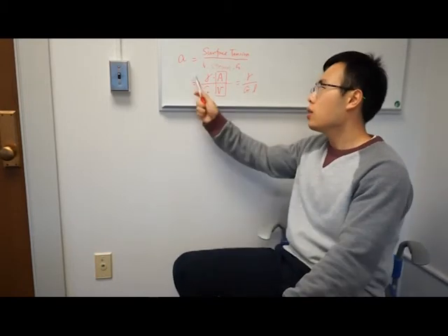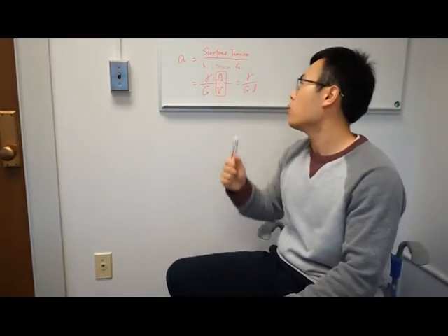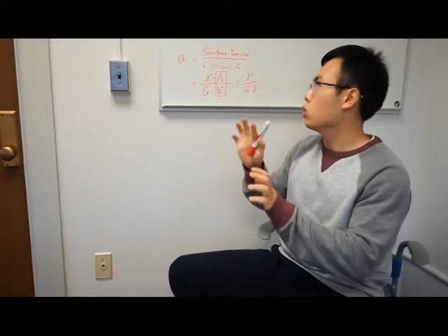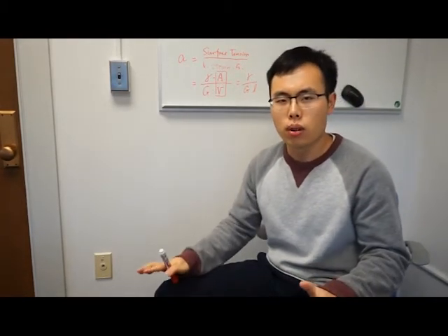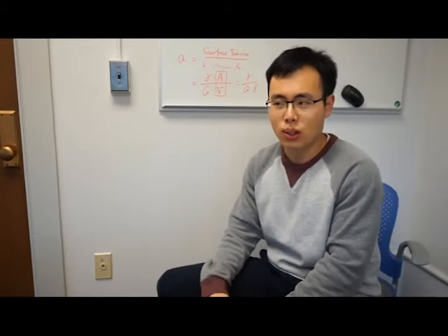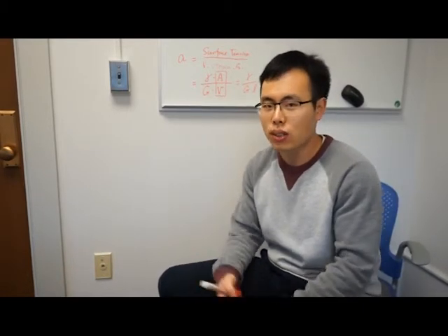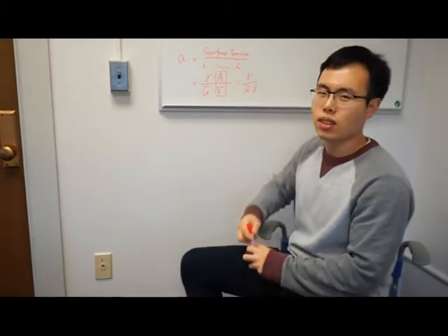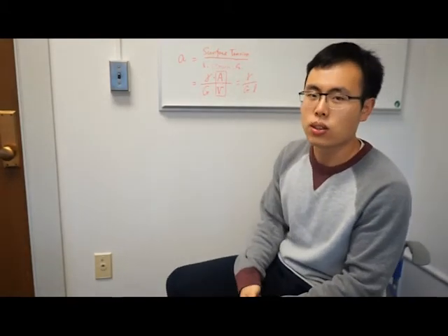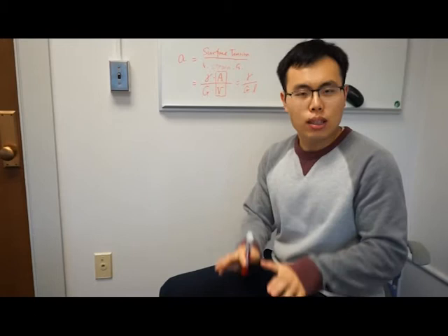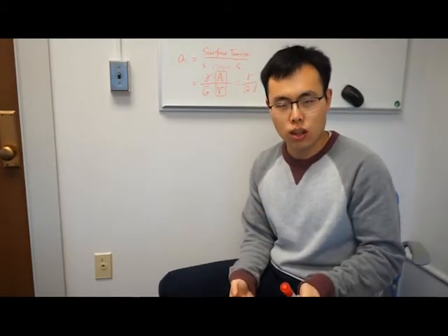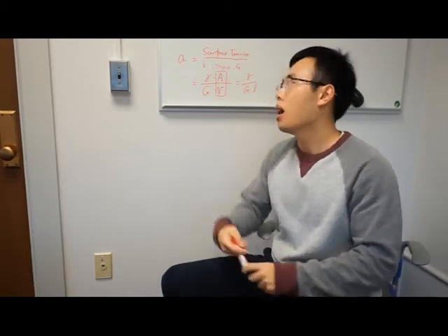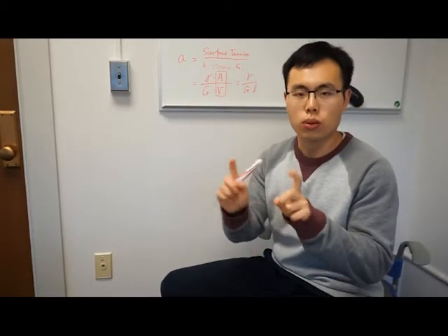But conversely, if A is so small, we have to mainly focus on the strain energy and can ignore the surface tension, which is happening all over the world, because many things are so hard and not soft solid. So the surface tension is not that big compared to its volumetric strain energy. But in this presentation, we're talking about things soft. We're saying the soft solids have this number around 1.